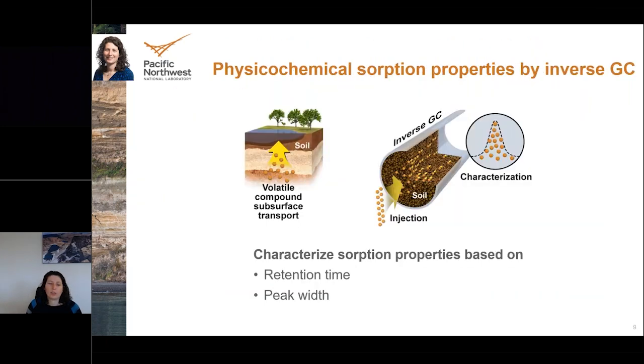So we're using inverse GC. The Earth's subsurface is much like a column of stacked materials, and we are using the IGC to emulate volatile compound transport. Just like a gas might migrate through a real-world soil column, we are using IGC to measure the level of interaction between the uncharacterized solid material and known probe gases by varying temperature, humidity, and carrier gas flow. What we did is we injected a pulse of a known probe gas through the packed column, and then determined the material absorption properties based on the width of the resulting peak and its retention time relative to an unretained species. And in this case, the unretained species is methane.